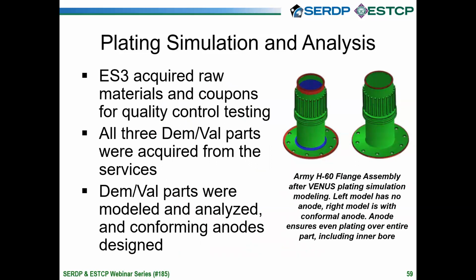Another component that we looked at is the H60 flange assembly. Like I said, that's a tri-service component. You can see a bit more simpler. So the design was simpler, but the blue area would be underplated. The entire inside of it is not going to get any plating at all, because when this is dropped in solution, all of your tank anodes would be on the outside of the part. So you can expect almost no plating on the inside. So we put a nickel rod down on the inside of that and then design. You'll see the fixture in a bit, but that plates everything theoretically very evenly. And you'll see where we plated this here at ES3's Georgia Technical Operations Facility in Warner Robins, Georgia, and everything plated very well.